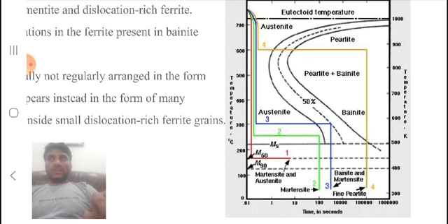But then the cooling rate is such that there is time for some carbon to come out of solution as carbide particles, as aligned particles within the lath at a fast rate, and the lower bainite is finer than the upper bainite, and as semi-lamellae between the laths at a slower rate, upper bainite is formed. Past research showed that such carbide-containing bainitic structures or tempered martensite structures were not superior to pearlitic structures for normal rail wear.